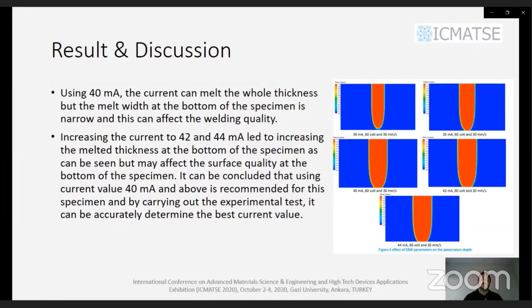So, using 40 milliampere, the current can melt the whole thickness, but the melt width at the bottom of the specimen is narrow, and this can affect welding quality. Increasing the current to 42 or 44 milliampere led to increasing the melted thickness at the bottom of the specimen, as can be seen, but may affect the surface quality at the bottom of the specimen. It can be concluded that using a current value of 40 milliampere and above is recommended for the specimen, and by carrying out the experimental test, the best current value can be accurately determined.